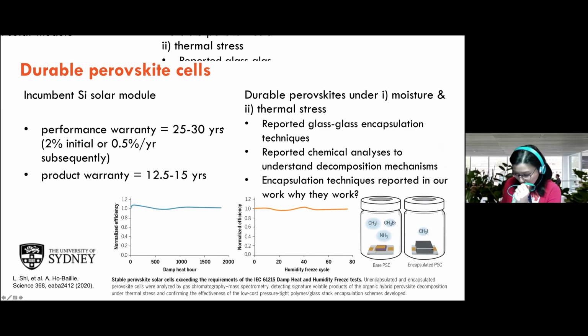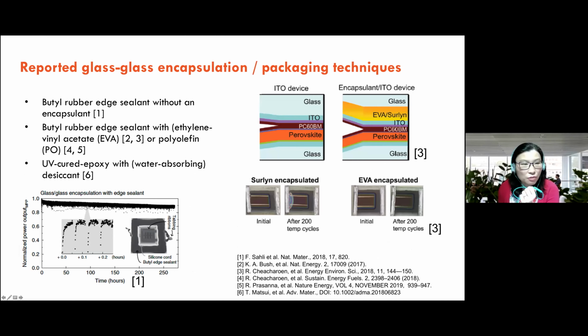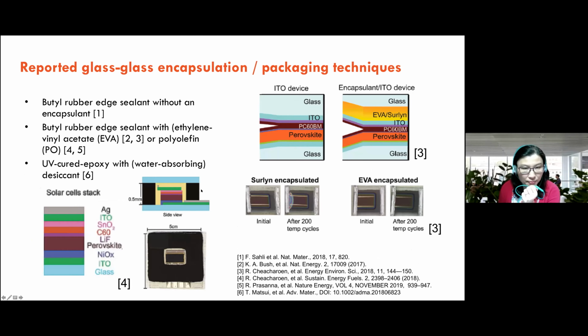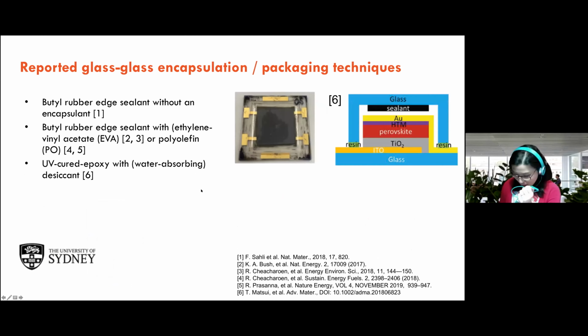So I'm going to talk about some of the glass encapsulation reported for perovskite cells, some of the chemical analysis used to understand decomposition, and the encapsulation techniques that were reported by us and why they work. So most of the groups report the use of butyl rubber as an edge sealant. So they either just seal the edge without any encapsulant, or they edge seal with an encapsulant, either EVA or PO, polyolefin layer. Some of them use UV epoxy with a desiccant, like a water absorbing material.